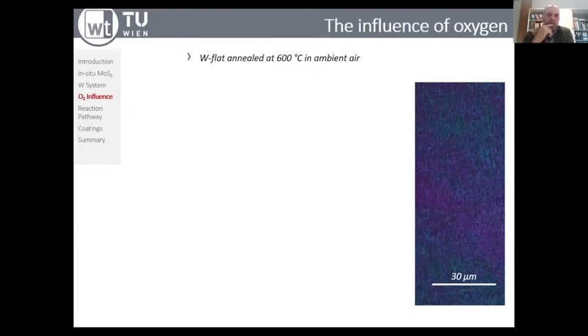So we try to say, okay, maybe something is going on with the role or the influence of the oxygen. So the next experiment, actually, what we did was to take a tungsten flat sample, and we annealed that at 600 degrees C under ambient conditions. And then, after 15 minutes of this thermal treatment, we created a very homogeneous, 500 nanometer thick tungsten trioxide film. So we pre-oxidized the tungsten surface, and then we checked what is happening after we pre-oxidized it.